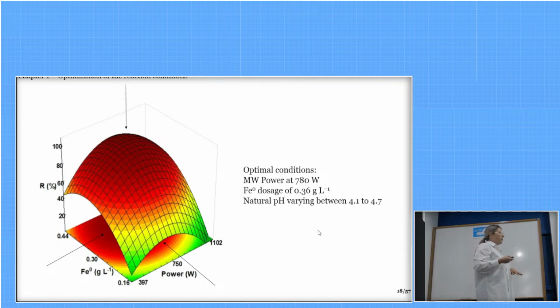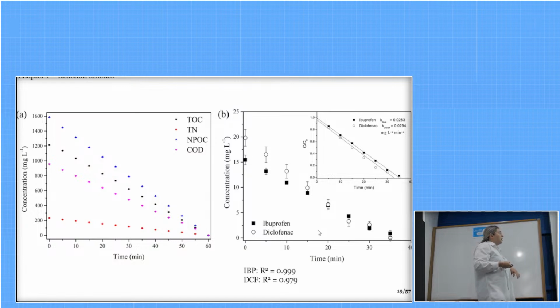The results pointed out that the optimal condition was found around a microwave power of 780 watts, a zero-valent iron dosage of 0.36 gram per liter, and the natural pH of the sample, which varied between 4.1 and 4.7. The reaction kinetics followed a zero-order model for all the studied compounds, being total organic carbon, total nitrogen, non-purgeable organic carbon, chemical oxygen demand, and ibuprofen and diclofenac. This is common when we have a medium that is really concentrated, so we are not able to see differences in the reaction order for any of the compounds.